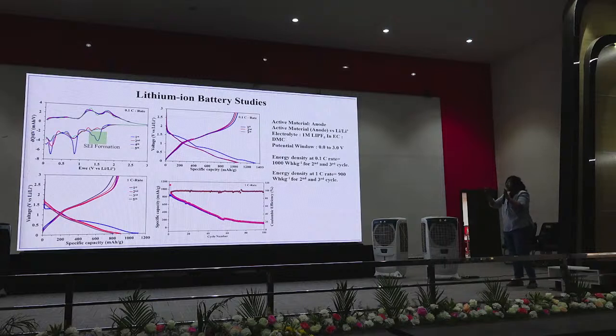Initially I have done 100 cycles. For the first 50 cycles a capacity loss has been found, and this is also due to the formation of the SEI, and the capacity stabilizes after the 50 cycles. We have got around 99.9% Coulombic efficiency for this.